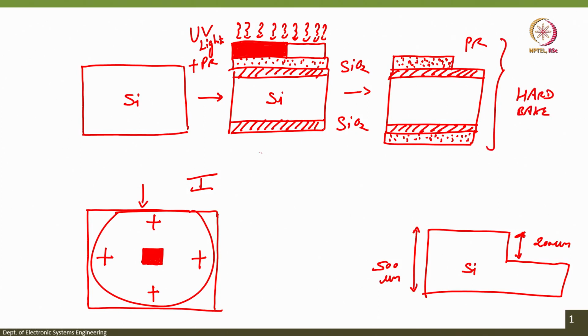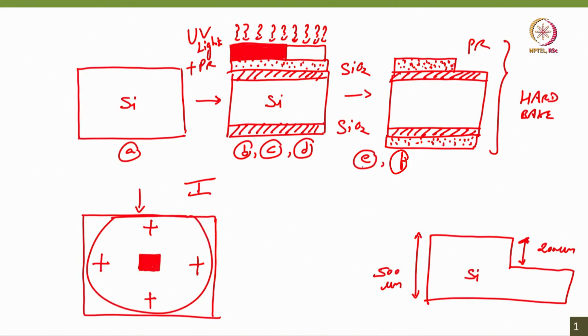So, once you perform this step A, then you have oxidized silicon B, then spin coating and soft bake C, then UV exposure, mask alignment and UV exposure D, then you perform the photoresist developing step which is E, then after photoresist developing step F will be, after you develop the photoresist you have to etch the silicon dioxide, right. So, for etching silicon dioxide, before that we will have a hard bake on both the sides. So, the silicon dioxide from the back side is protected when you dip the wafer in BHF.